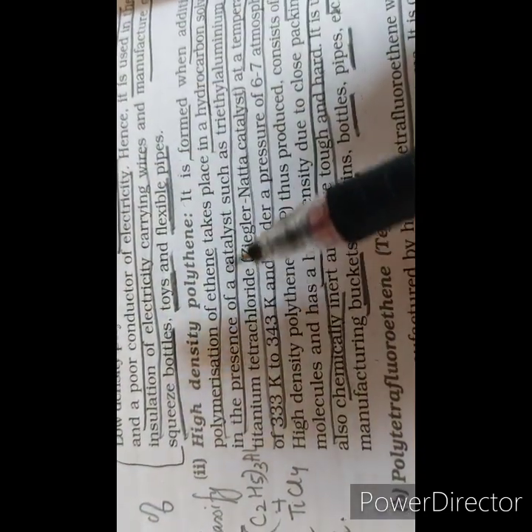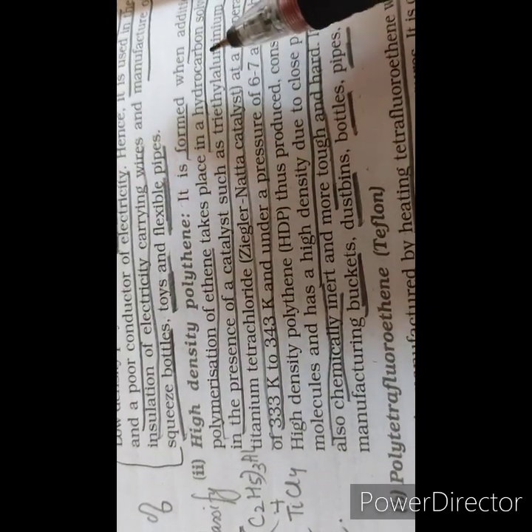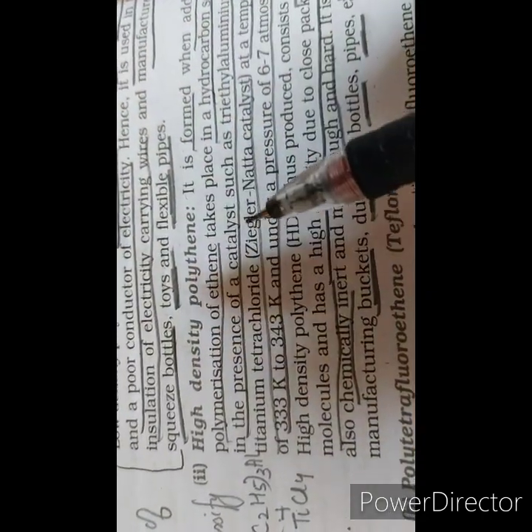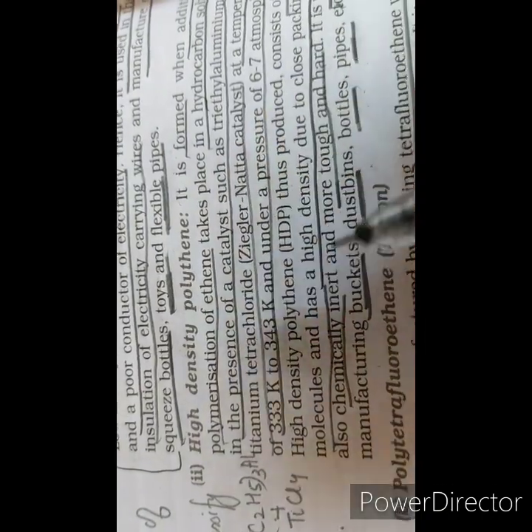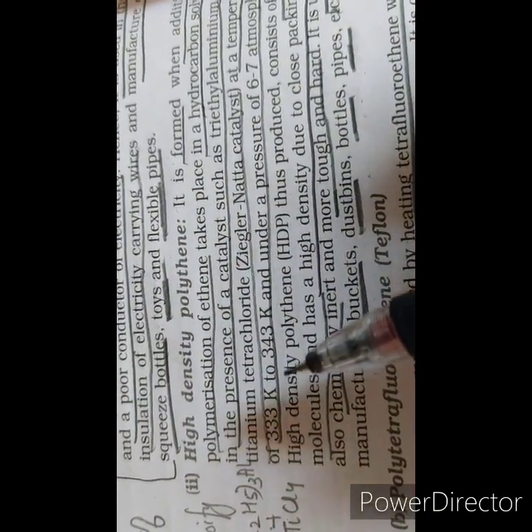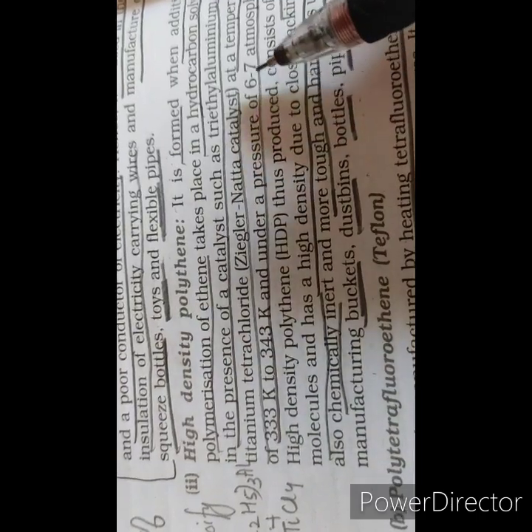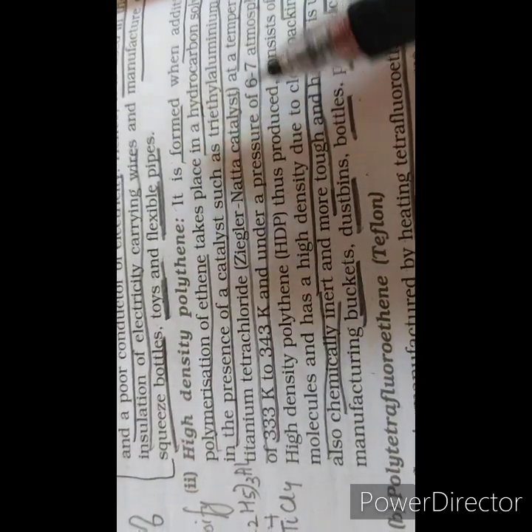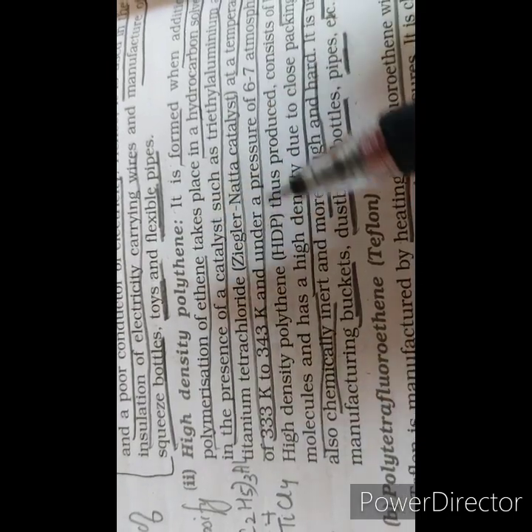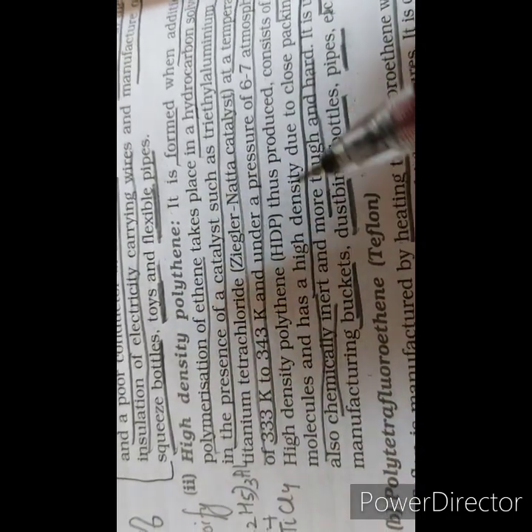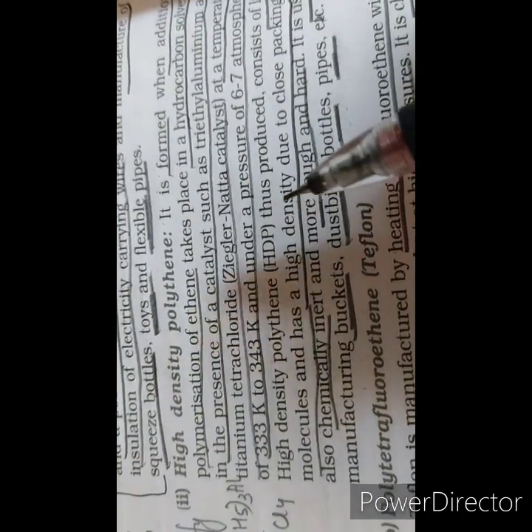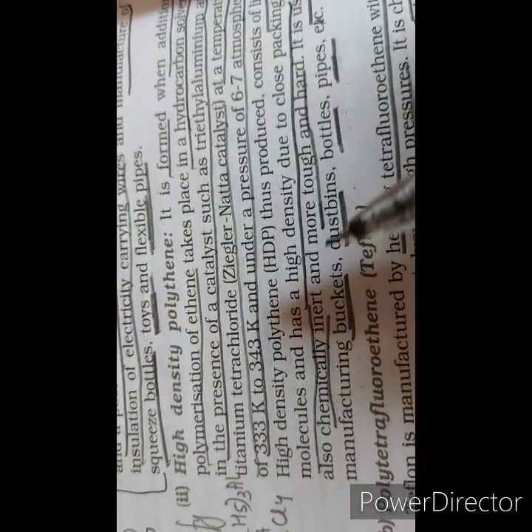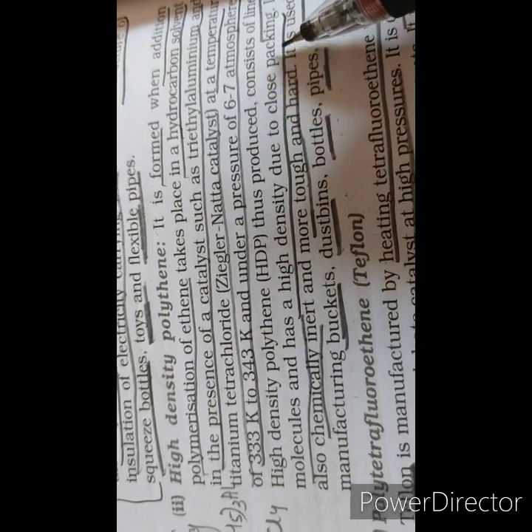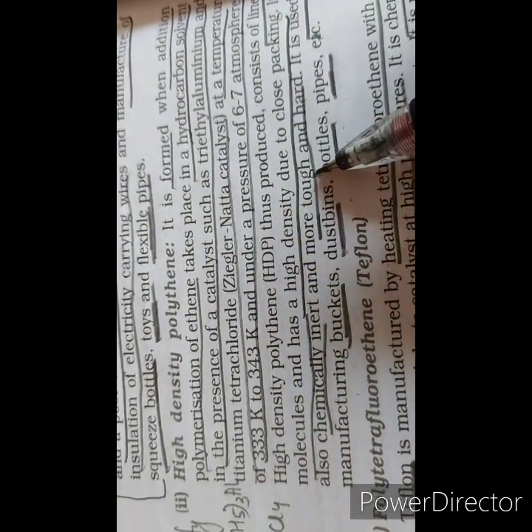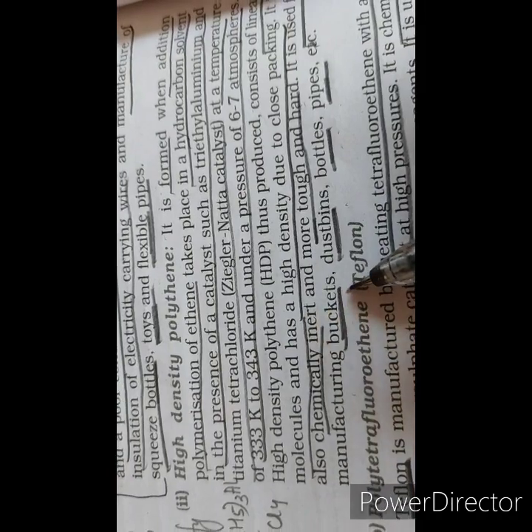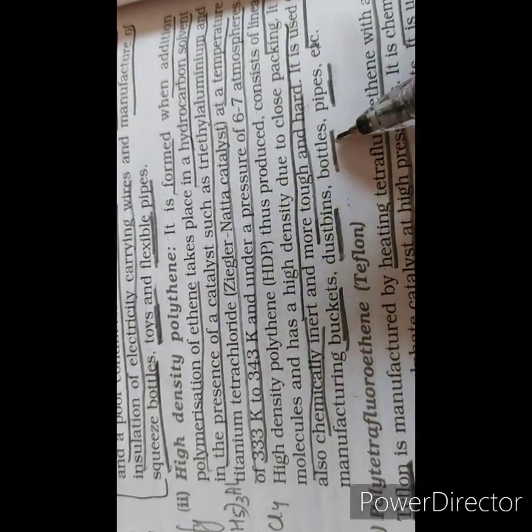So it is formed when addition polymerization of ethene takes place in a hydrocarbon solvent in the presence of a catalyst such as Ziegler-Natta catalyst, and the temperature is 333 Kelvin to 343 Kelvin and pressure is 6 to 7 atmosphere. So you can understand the contrast between the preparations of the two, low density polythene and high density polythene. This high density polythene is linear molecule. It has a high density due to close packing. It is chemically inert, more tough and hard, and it is used in the manufacture of buckets, dustbins, bottles, pipes.